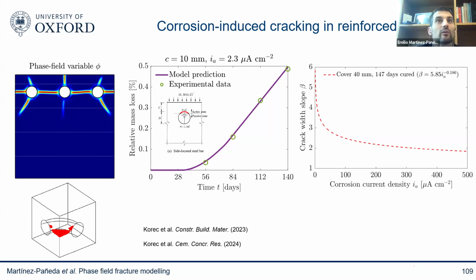We normally do accelerated corrosion tests in our labs. But if we can capture the physics of the problem, we can make sure that the model agrees with accelerated corrosion tests, and then take that model to simulate the scenarios of natural corrosion. So then predict what's going to happen in civil engineering infrastructure over decades.